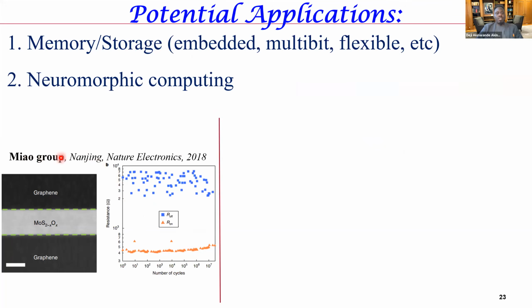Feng Miao's group in Nanjing, who I visited last year, has shown that by doing some chemistry, in particular small oxidation of the MoS2, you can improve the endurance of this effect, how many times you can cycle it, from hundreds to millions. So we're trying to apply now this idea to monolayer films.